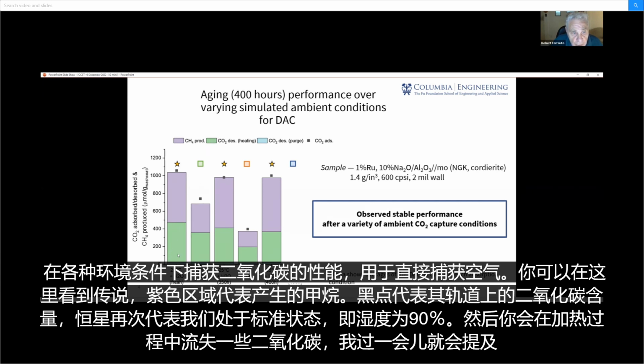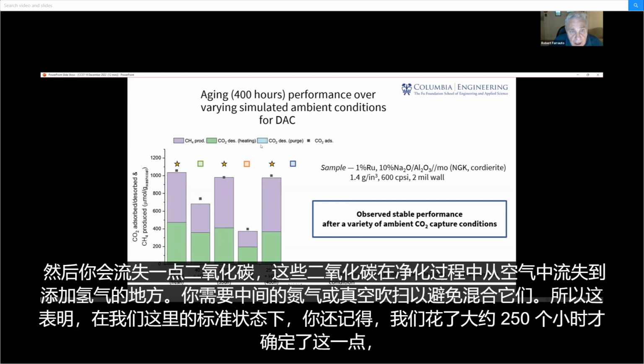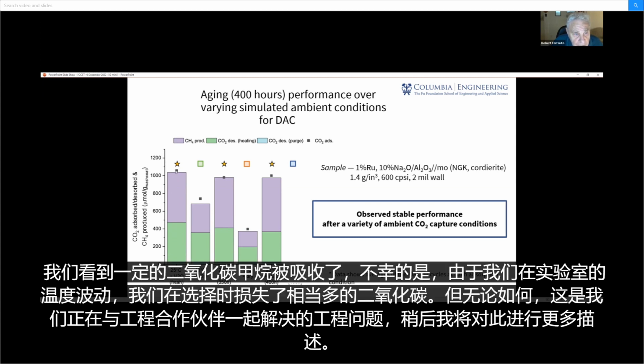And then you have some CO2 that you lose during the heating, which I'll be mentioning in a moment. And then you have a little bit of CO2 that you lose during the purges, where you move from the air to addition of hydrogen. You need an intermediate nitrogen or a vacuum purge in order to avoid mixing these. So what this shows is that in our standard condition here, and you recall we worked for about 250 hours establishing this, we see a certain amount of absorption of CO2, methane, and unfortunately, because of the temperature swing that we do in the laboratory, we lose quite a bit of the CO2 during the desorption. But in any event, that's an engineering problem that we're addressing with our engineering partner, and I'll describe a little bit more about that later on.